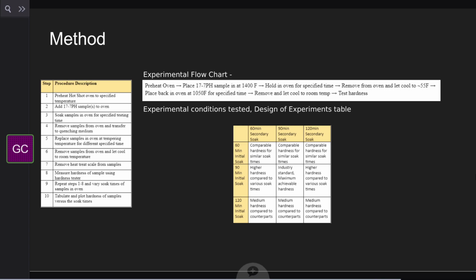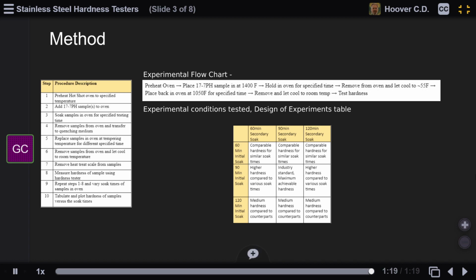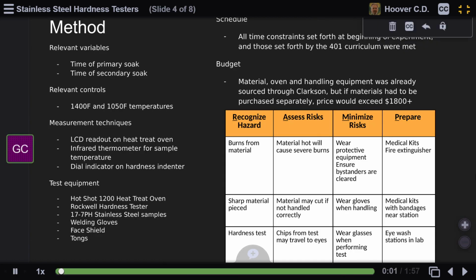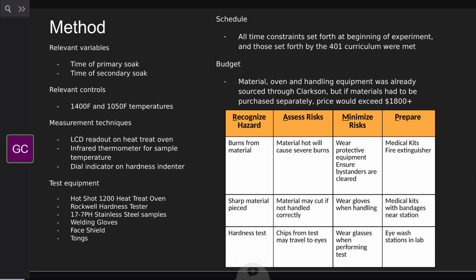We started right in the middle at 90 minutes for an initial soak and 90 minutes for a secondary soak, and then deviated 30 minutes both upward and downward from that, giving us 9 total samples. In terms of relevant variables, the times of the primary and secondary soak were our main factors we were changing, and our controls stayed the same. Those are the 2 temperatures in the oven: 1400 degrees Fahrenheit for the initial soaking temperature, and then 1050 degrees Fahrenheit for our secondary soak temperature.